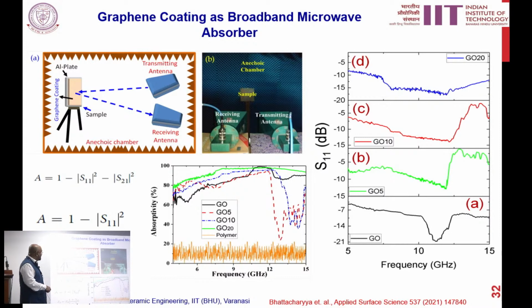So here is the measuring setup inside an anechoic chamber, where we have a receiving antenna and a transmitting antenna, and the interesting results are here. These all are the calculations. Basically, here you see the absorptivity. With different frequencies, you see the absorptivity is almost 100%. So by increasing graphene, having some sort of magnetodielectric interface along with a defect, they basically absorb the whole electromagnetic radiation, and could be used for a good sprayable composite coating.